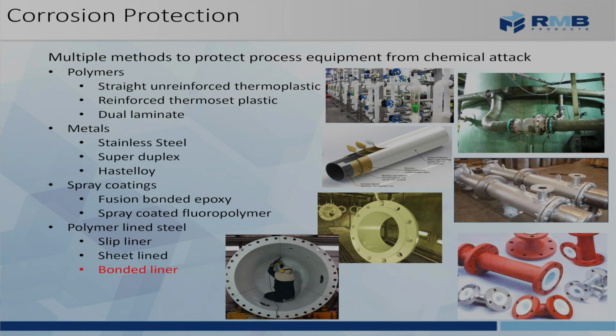So corrosion protection, you're hearing all about FRP and dual laminate this week. Great content and information, even some straight thermoplastic information this week. And those are great materials for corrosion protection. Sometimes, I know customers will need to use stainless steel or super duplex or Hastelloy for service environments. Sometimes you'll even use a spray coating like fusion bonded epoxy or a spray coated fluoropolymer.